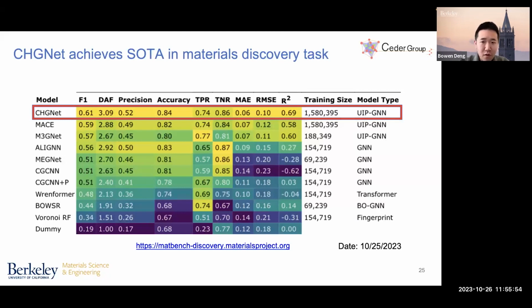R squared. So first of all, these numbers are not just the errors that we predict on the structures. We get these errors by taking the same initial structures and relaxing them, and we compare their final energies with the DFT relaxed energies. So there are two factors of errors, one coming from the different relaxation and one coming from the static calculation of the final frame. If you combine both aspects, this 0.7 R squared, at the scale of the data set that we have currently, is actually the highest R squared that we can achieve.